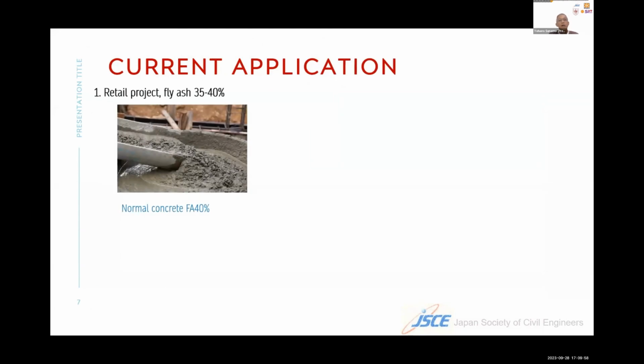In our current application now, we already use fly ash with a percentage of about 35 until 40%. So for the retail project, we always use a fly ash content of about 35 until 40%, except if the project has special requirements.